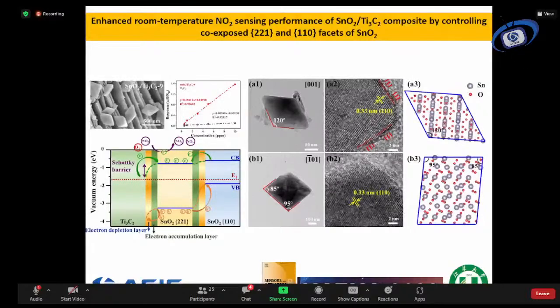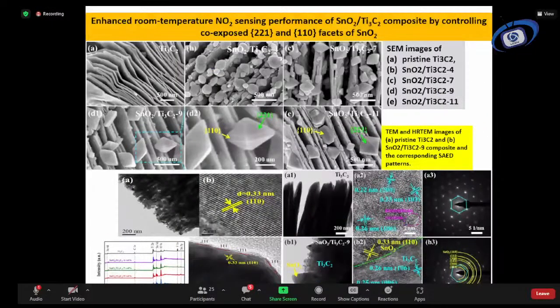Typical figures are also shown here for the Schottky barrier, and also for TEM and HRTEM, and for the simulation, the one for the quantum effect as well. You can see here detailed structures for different samples with different constructions. They show ultimately uniform nanostructure from the synthesis process at the initial stage. And at the bottom, the XRD figure has been shown as well.